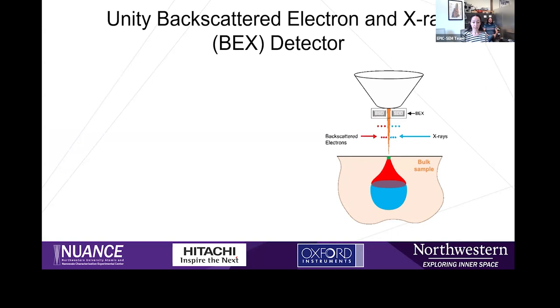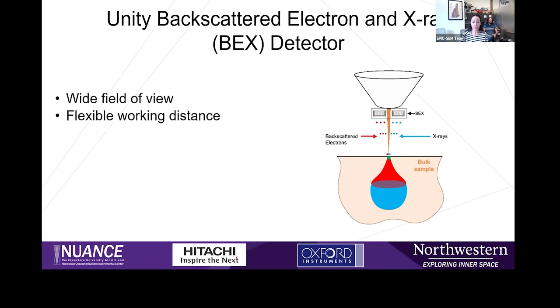Because it's directly underneath the pole piece, the field of view is much wider. You can even do fisheye images. The working distance is also flexible. You don't have to work at just that specific working distance to make sure the X-rays get into the detector. There's also no shadowing typical of EDS because it's not placed on an angle. It is directly above.